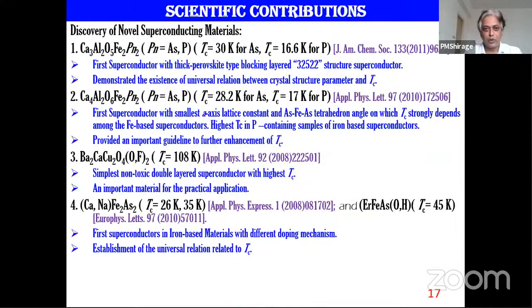So as I mentioned, superconductors. In an earlier slide, I told you about the high pressure synthesis technique. That is one of the important techniques that can be used for making new materials. These are a few materials which I discovered using this technique. These are completely new superconductors: calcium 3, aluminum 2, oxygen 5, iron 2, arsenic 2. Basically, when we have iron in a material, that kills the superconductivity. But this superconductor has iron inside it, and that is very interesting. This is called the 32522 superconductor.